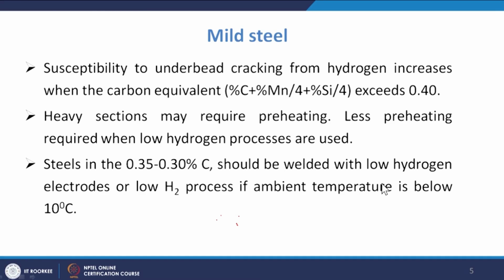So why do we have to provide preheating? So that the cooling rate will be reduced. If the cooling rate is reduced, the martensitic formation will be reduced. Less preheating is required when low hydrogen practice is used. And also if the cooling rate reduces, any diffused hydrogen has enough time to diffuse out. Okay, so steel with 0.35 to 0.3 carbon content should be welded with low hydrogen electrodes or lower H2 producing electrodes if ambient temperature is below 10 degrees centigrade.